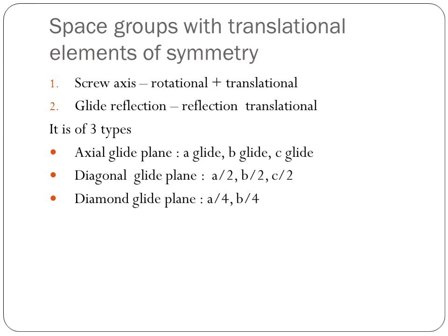The second one is glide reflection. This refers to a symmetry element called a glide plane. In three dimensions, the glide plane gives the result of reflecting a point through a plane and translating in the direction of a lattice vector. That is, reflection, and due to this reflection there is a translation. The translation is restricted to 1/2 of the lattice vector length, because repeating this operation has to bring the initial point into coincidence with an equivalent point. That is, the translation will be half of the lattice vector along the reflection plane.